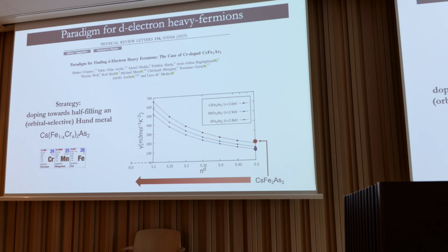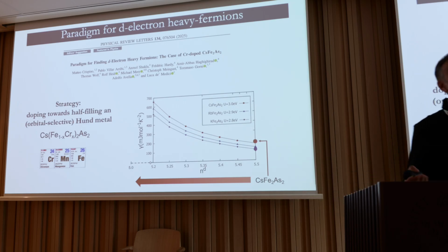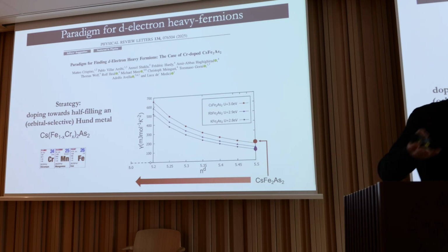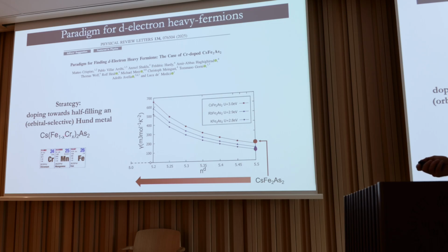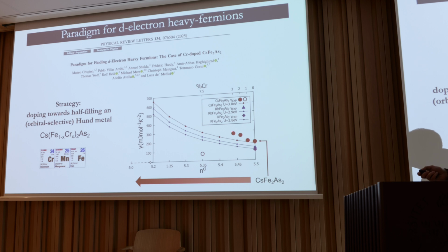The reason is that this was already done for barium-122, and it works. It's very nice because it doesn't change the lattice spacing at all, or almost. So it really only introduces holes in the plane and some disorder, unfortunately. The group of Karlsruhe was able to synthesize these single crystals in several compositions. Here are the results for the Sommerfeld coefficient: for 3% chromium, despite solubility issues, they got a record, at least for the iron-based family, of 270 millijoule per mole Kelvin squared.